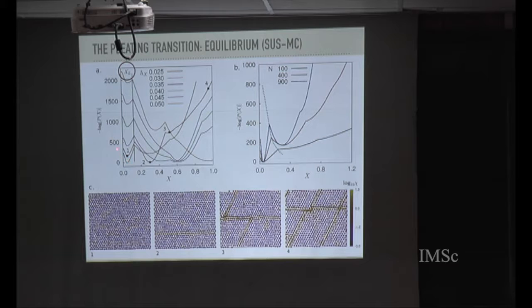So for small values of the field, there is only one minimum, but as you increase the field, other minima appear. And then at some point, there is a very typical first order transition. And I would like to point out that there is a saddle point, and the value of the non-affine parameter at the saddle point doesn't seem to depend on the field. So there is one saddle point which is the maximum non-affineness that a crystal, or an ordered structure, can take. And once it is exceeded, it forms a pleat.